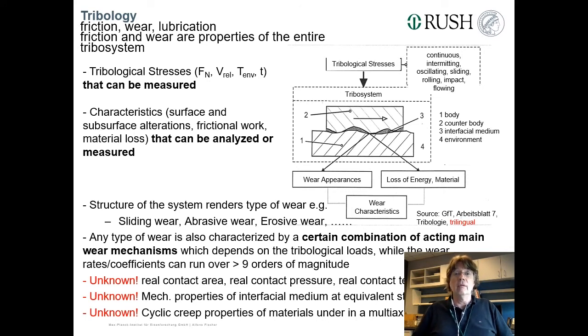Again, the shear rates are larger than 10 to the power of 8 per second. And think about whatever method to measure the properties of something which could be a mixture of everything and seriously contaminated by dirt and all of that. How do your stresses and strains react under shear rates of that magnitude? I wouldn't know any, so if you have a brilliant idea, just let me know. And below that, there might be something taking place that we call ratcheting or cyclic creep under a multi-axial cyclic stress field. And this plays together, and we do not really know the interdependencies.